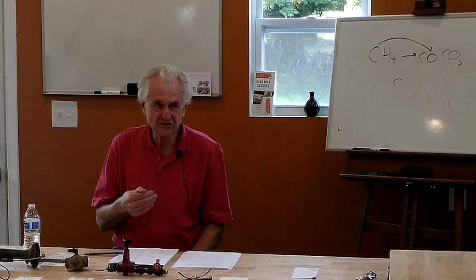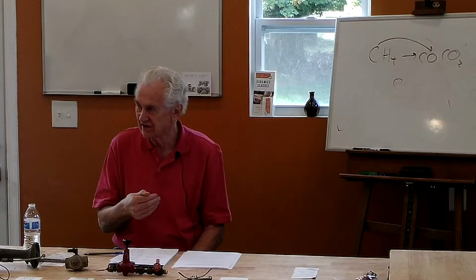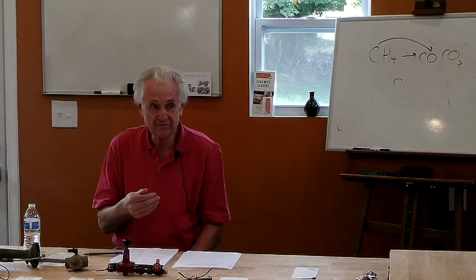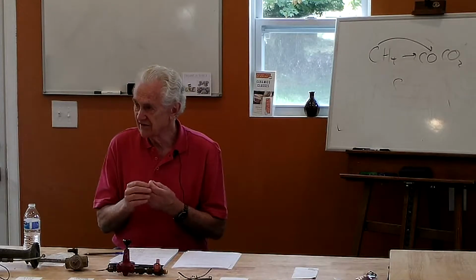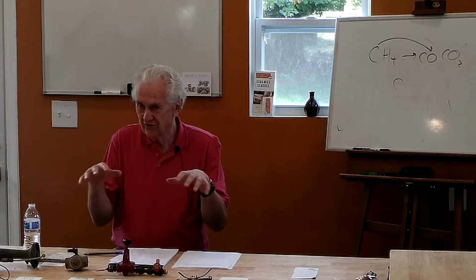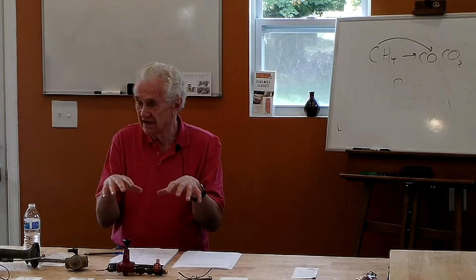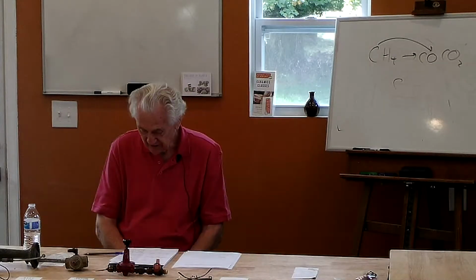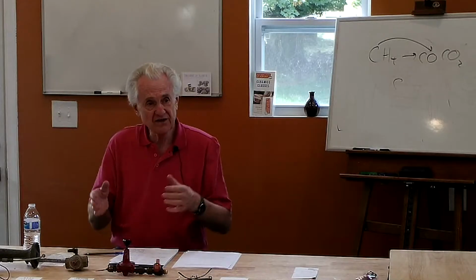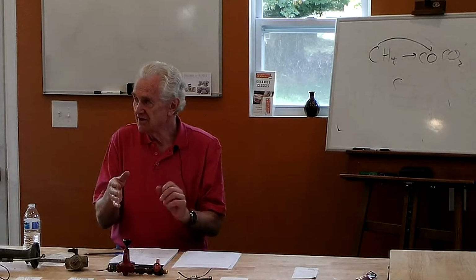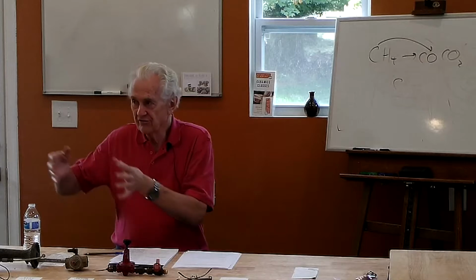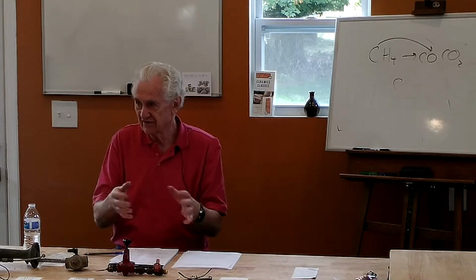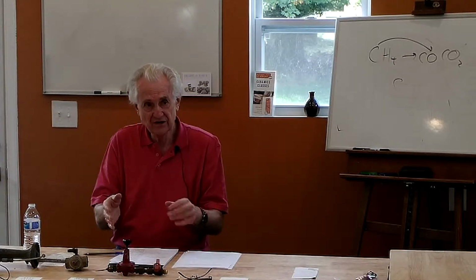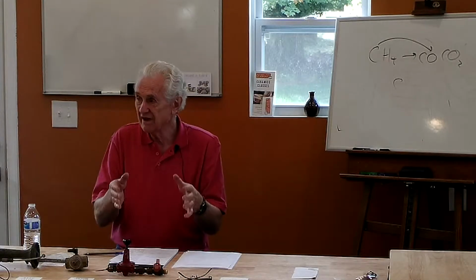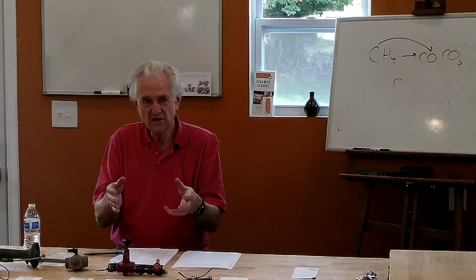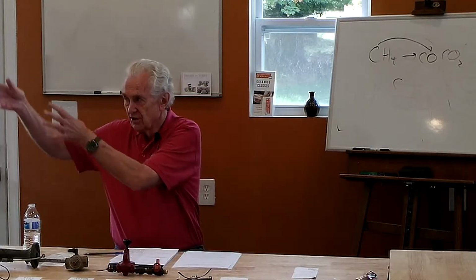If you don't do reduction early enough, if you started at like 06, in a lot of cases, that's too late. Because the things have already started to seal off or close up, and the gases can't adequately penetrate the clay and the glaze, and you won't get good color. You need to maintain reduction. After you do your early reduction in the firing, you can't go back into oxidation to do the whole rest of the firing, or you'll lose, before the glazes have completely melted, a lot of the early reduction. So you have to maintain reduction. You do your body reduction, and then you maintain some reducing atmosphere all the way up to the end.